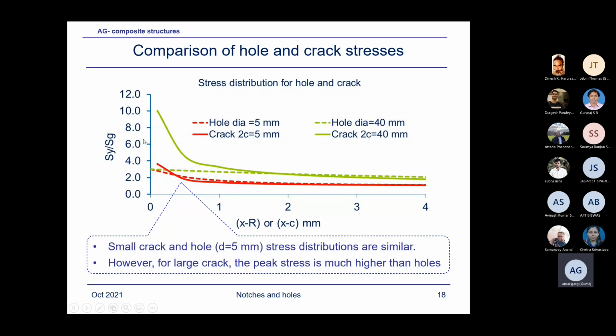But for the crack, this stress keeps on increasing significantly, and in this region, very high stress. What this tells us, naturally, if you look into this stress distribution, is that a 40 millimeter hole doesn't seem to be as critical as the 40 millimeter crack here. Whereas a 5 millimeter crack and a 5 millimeter hole might land up with the same residual strength. So that will be the difference between the crack and the hole.